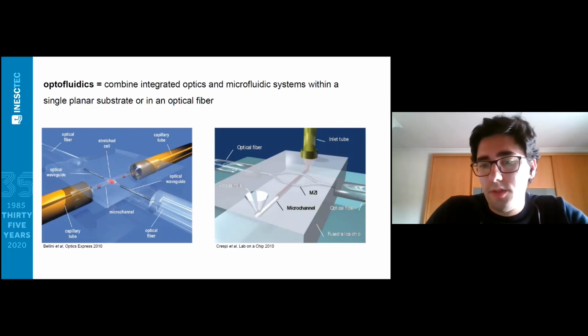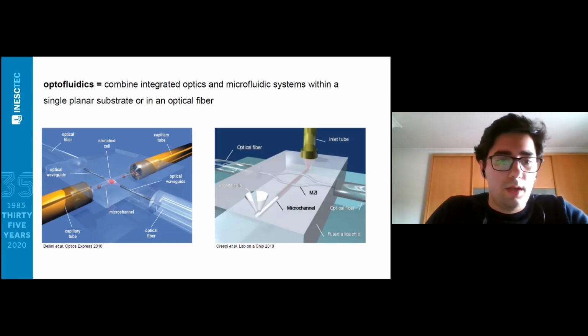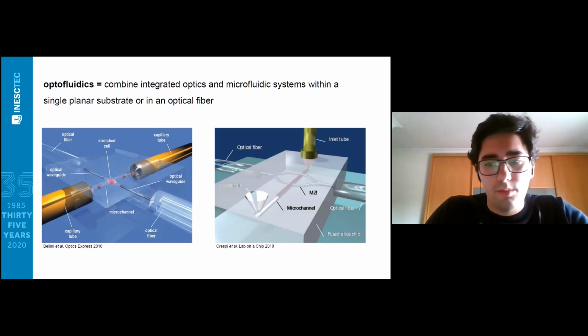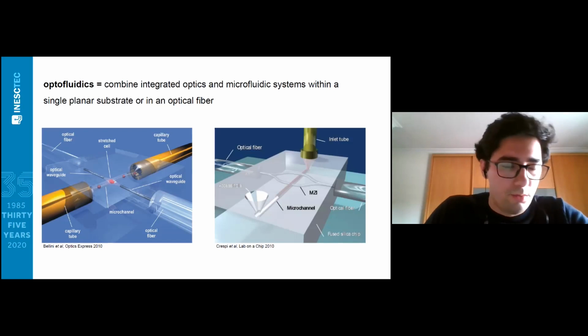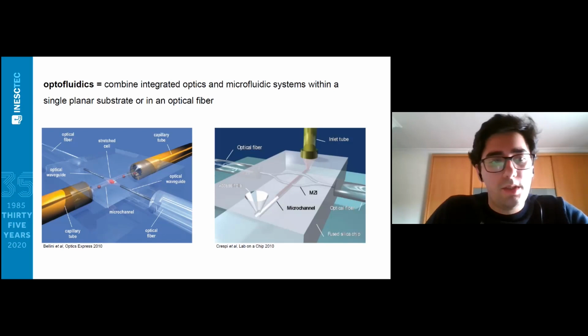In another application, also made in a fused silica substrate, you have a Mach-Zehnder interferometer where light travels from an optical fiber into a Y junction, which splits the guided beam into two arms. One of those crosses a microfluidic channel, whereas the other goes above the channel, and at the output both signals recombine. By changing the refractive index within the microfluidic channel, you can change the interference condition, and that way we can measure through the output spectrum any variation in the refractive index of the fluid, which can be caused by alteration in the concentration of, for instance, an agent mixed within the fluid, or alteration in temperature, or whatever.